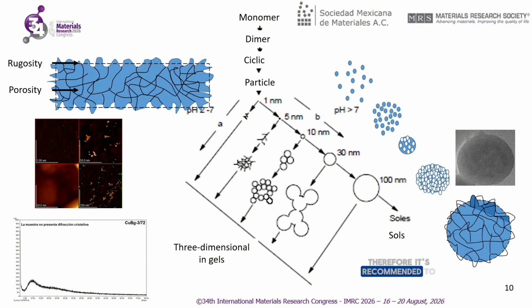Therefore, it's recommended to use particles obtained via the Stöber method, and it is even advised not to resort to an in situ hybrid synthesis. The bioglass nanospheres obtained by the basic catalysis exhibit intraparticle and interparticle nanoporosity, as well as metal ions such as calcium 2+ and magnesium 2+, that induce an amorphous structure in the bioglasses.